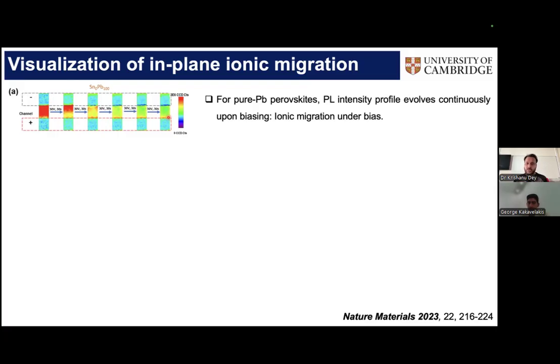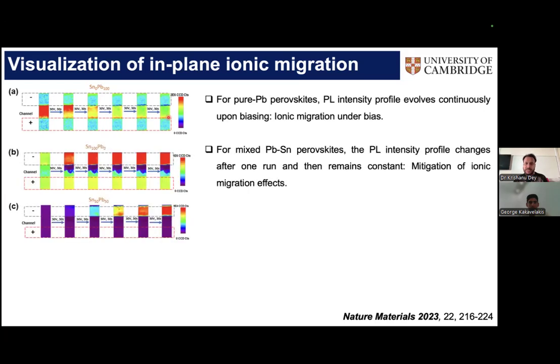And this is a well-known technique in the literature to probe ion migration in different compositions. So then we did the same measurements, but now for the mixed lead tin perovskites. And you can see that for the mixed lead tin perovskite, generally there is a little bit of change after the first cycle, but after that, the behavior is pretty much constant. So there is no further change that happens after the first biasing cycle. So it tells you that that ion migration behavior is definitely present, but it's certainly much slower or suppressed, let's say, than the lead-based perovskites. We see the same behavior for the mixed lead-tin perovskites.